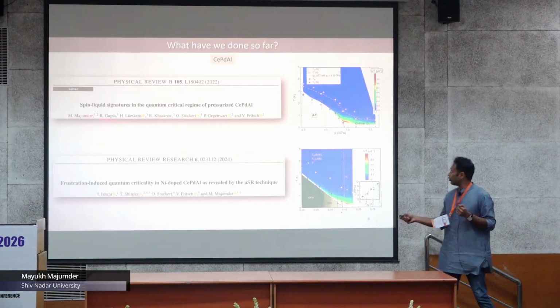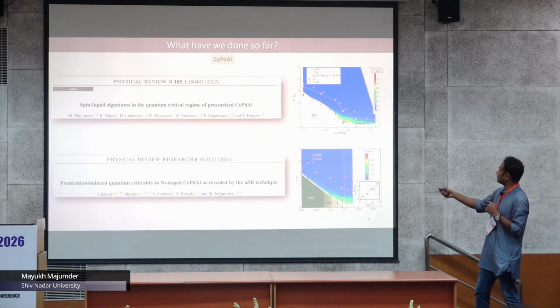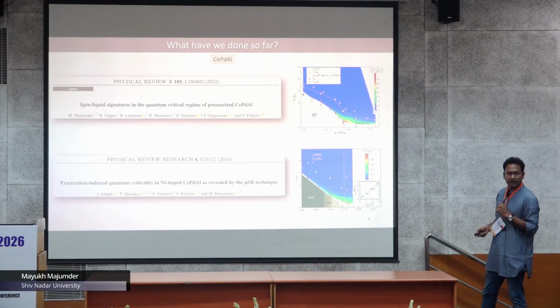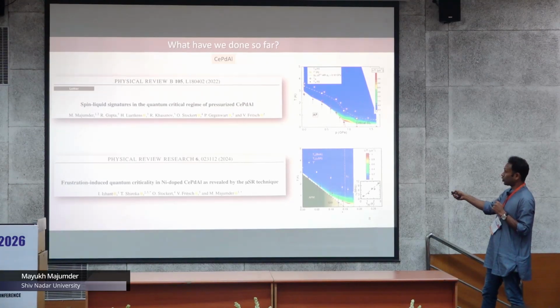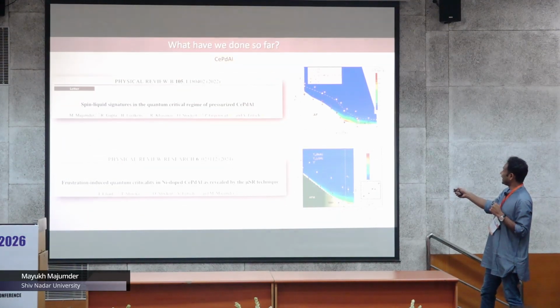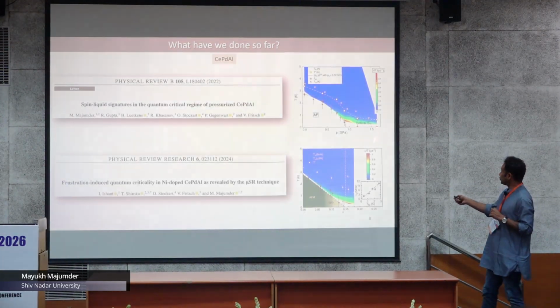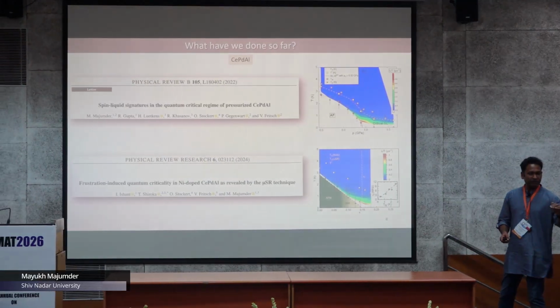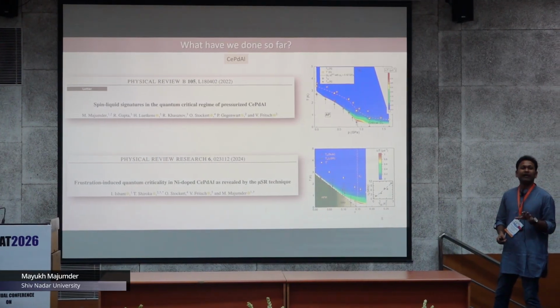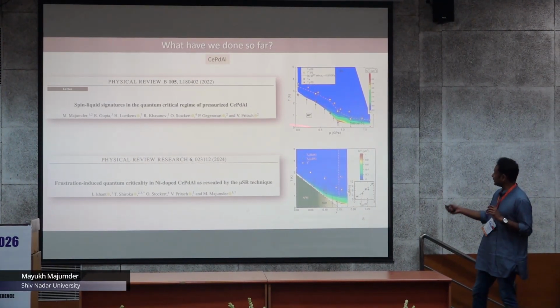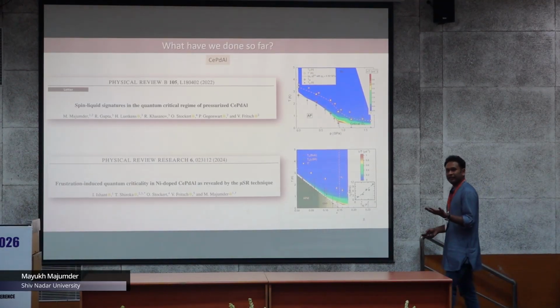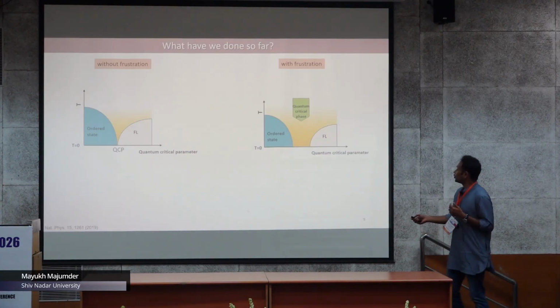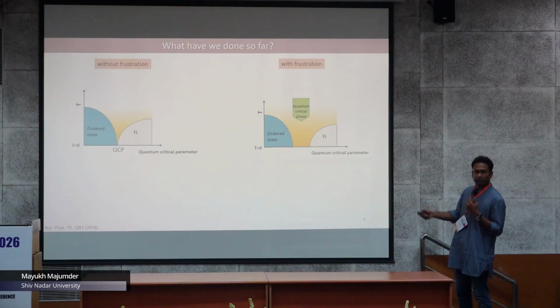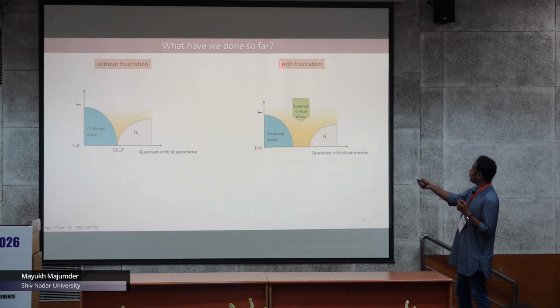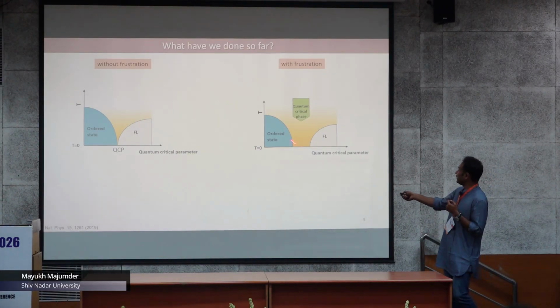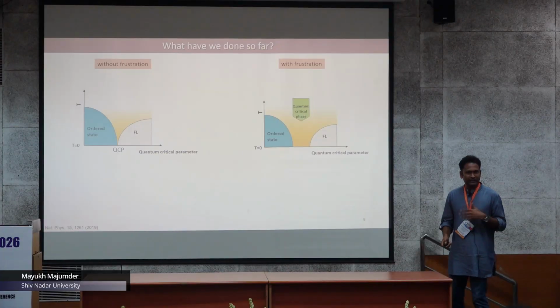We invested a good amount of time utilizing muon spin relaxation, and interestingly we saw that both chemical pressure and hydrostatic pressure can suppress the ordering, but most interestingly, at least down to 50 millikelvin, we didn't see any appearance of a Fermi liquid state. Rather, we saw an extended quantum critical phase. This was the phase diagram that I already showed. So probably because of the presence of frustration, you have an extended quantum critical phase.